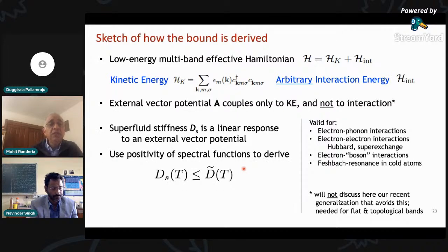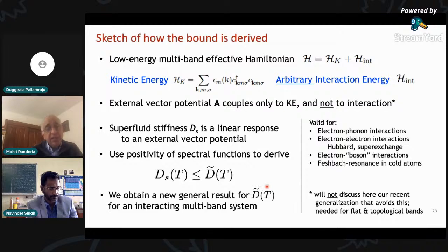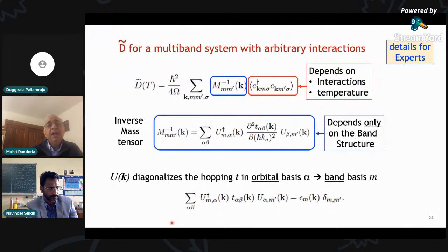And then technically, we want to compute the superfluid stiffness, and it's the linear response to a vector potential. We write down a Kubo formula and use the positivity of spectral functions to derive the bound, which I explained intuitively using some rules on the previous slide. So the superfluid stiffness is bounded by the optical spectral weight. In the process, we obtain a new general result for the optical spectral weight of an interacting system. This is really details for an expert, but it is a result where, for arbitrary dispersions and arbitrary interactions, we can figure out what D tilde is, this upper bound on the superfluid stiffness. And despite appearances, this quantity is much, much easier to estimate for various systems.